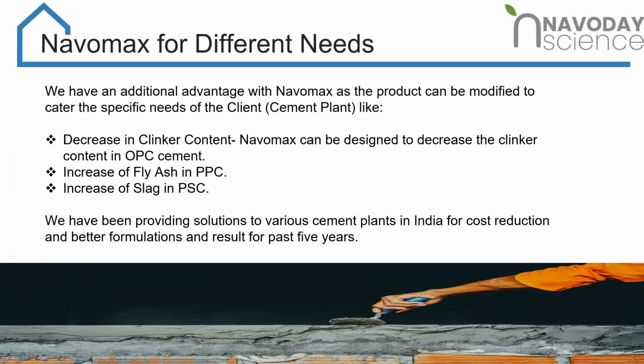So Navomax can be used for different needs depending upon the individual needs of the cement plants. It can be used to decrease the clinker content, or it can be used to increase the fly ash in PPC and slag in PSC. People have been using this to increase the fly ash and the slag, and it has also been used as a waterproofing additive to promote a new type of cement called waterproof cement in the cement industry. Next slide, madam, please.